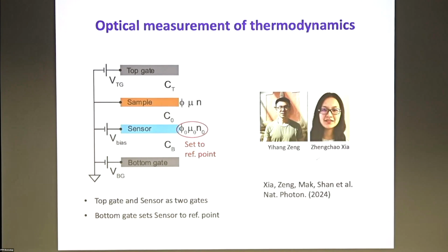At the beginning, we were not able to make very good contacts to the material. So we used an optical method to read out locally the chemical potential of the system. Okay, so how it works is the following: in addition to the sample, we put a sensor, which is separated from the sample by a thin layer of boron nitride. So the two are not touching each other, but are separated by a thin dielectric layer.